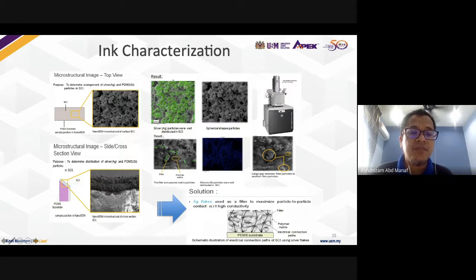At that time, they did some study on mixing silver nanoparticles with the ink, and then they did homogeneous mixing. This is a cross-sectional view, the SEM image, and the green color is a filler, that means the silver nanoparticles, but you can see they have a gap. When they have a gap, that can reduce the conductivity.